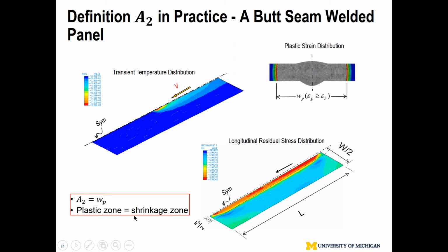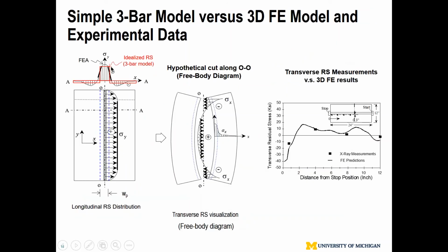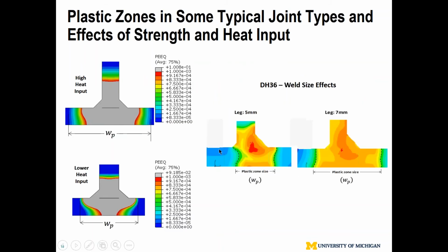Again, let me extend it a bit because of time. Actually, what is the heated area? When we do welding, we have molten material, and then we have material beyond the weld zone that gets heated. So this is Wp or A2 here, in reality representing the plastic deformation zone. This is aluminum alloy, about 1/4 inch thick. Simulating that process using a computer model, the plastic zone far exceeds the width of the weld zone. So the key message here is we worry about shrinkage and distortion, not just from the weld metal. Actually, it is the metal surrounding the weld zone, the plastic zone. That plastic zone is a shrinkage zone.